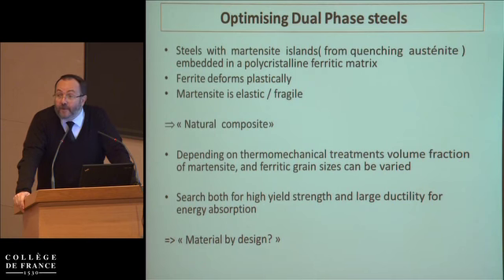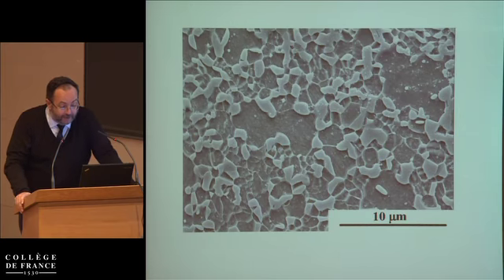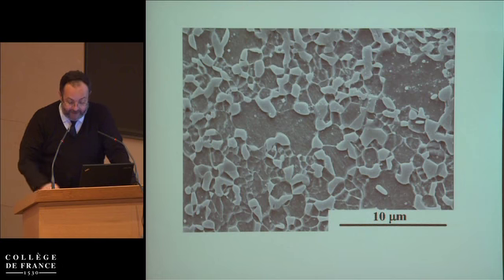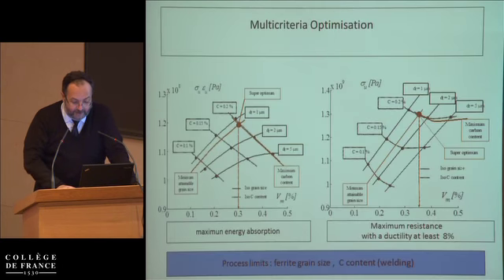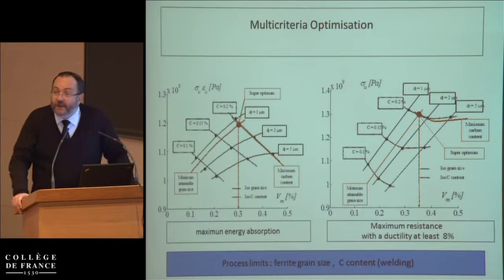Now, depending on the thermomechanical treatment, you can change the volume fraction, the hardness, the shape, the scale of the various phases. And that's going to give you some tools for material by design, designing this composite from the process of the microstructure. Now, here is the microstructure, okay? You have this mixture of ferrite and martensite. And now, what I want to show you is the kind of optimization you can get.